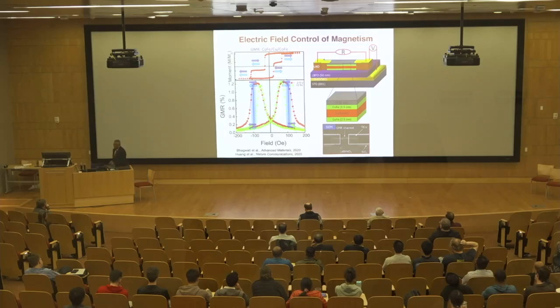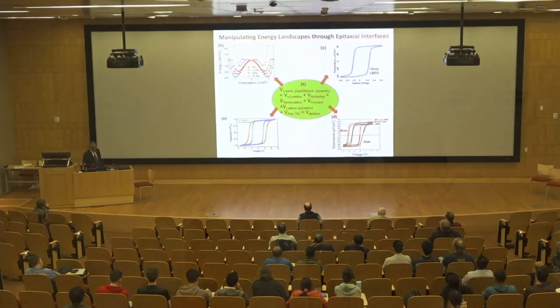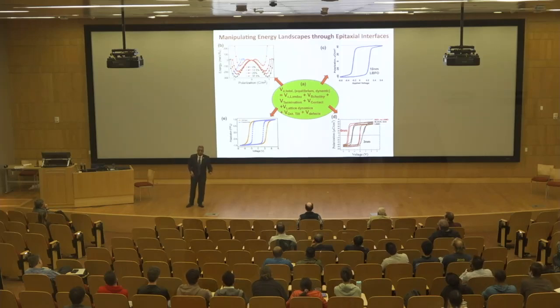Okay, with that, you could say, what else can we learn about this? The first question was, how does one go from 2.5 volts down to 100 millivolts? And we still don't know completely how to go to 100 millivolts. But we know that one can tune the Landau potential by chemical substitution. So you can use crystal chemistry, very classical approaches. Take bismuth out and put lanthanum into the structure. And you can tune the double well. And that indeed impacts the hysteresis.